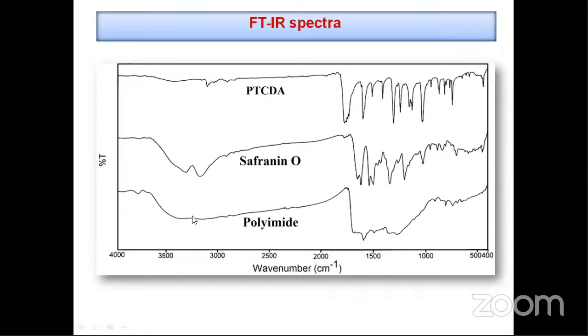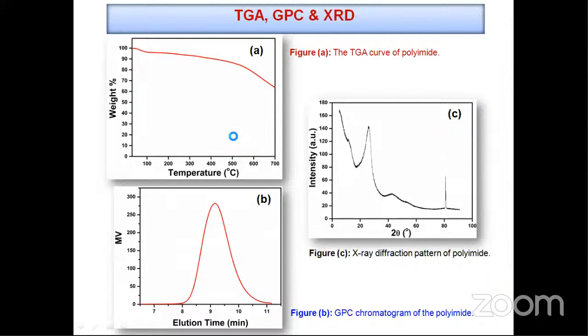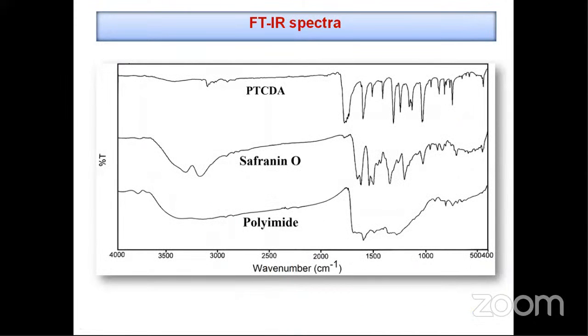But in the IR spectrum of the polymer, the NH stretching vibration has completely disappeared, and the carbonyl stretching vibration of the anhydride group has also disappeared, and a new peak appeared at around 1600 centimeter inverse, which corresponds to the carbonyl stretching vibration of the imide group. So here the disappearance of the amine NH stretching vibration and the carbonyl vibration of the anhydride group indicates the formation of the polyimide with complete conversion of the monomers.